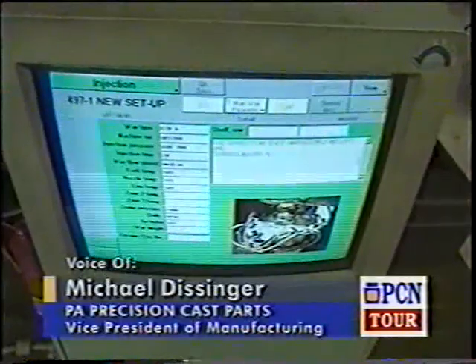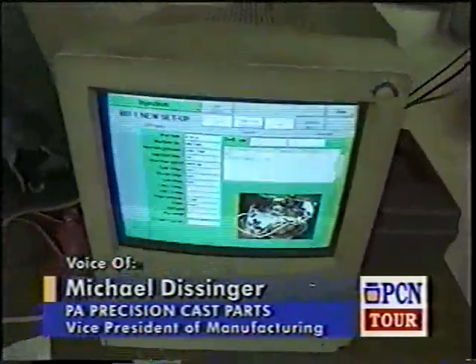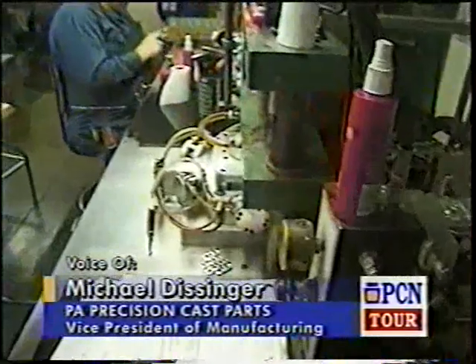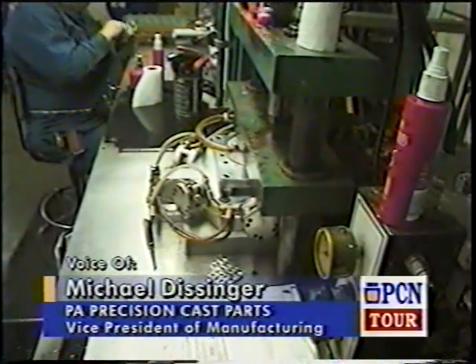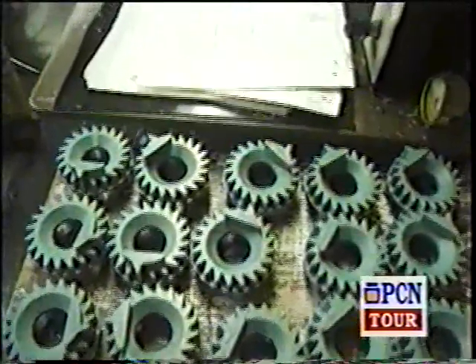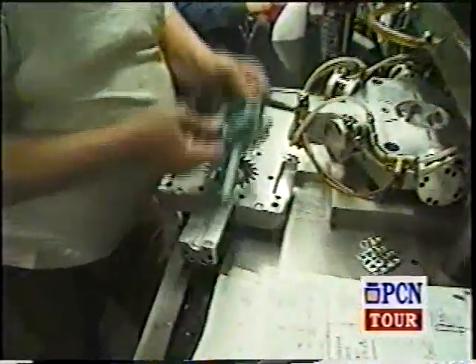We are now in our wax injection department, where we take that liquid wax that is pumped to each individual machine. The wax is injected under pressure at about 140 degrees. We do have some machines that actually temper the wax down to about 132 degrees. That's called a paste wax. It's the same wax, just starting at a little bit colder temperature, which decreases the dwell time and therefore makes the process go a little bit quicker.